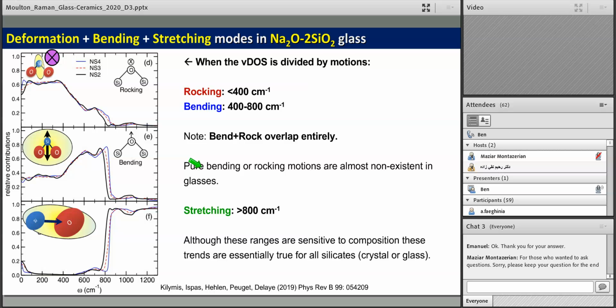But we can not only divide by bridging and non-bridging oxygen, we can divide by the motions we talked about earlier. So in their simulations, again from the same study by Kilymis from last year, if we divide the motions by rocking and bending, we see that from 0 to 800, we have an intense region from 0 to 400 with a lot of rocking. That continues to 800 wave numbers. The bending shows the inverse behavior, where it has moderate contributions at low frequencies and then increases the contributions in the center of the spectra. Both of these become almost zero and don't contribute to the stretching region above 800.